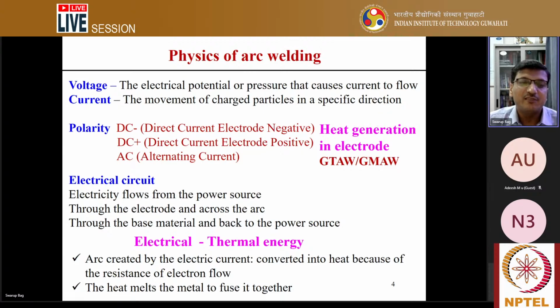So with this alternating way, both the cleaning action as well as the welding action are possible in the case of low melting point material having high affinity to form oxides. So aluminum is more suitable with AC current. We can use AC current specifically when you try to join aluminum. Anyway, fusion welding of aluminum itself is difficult, not easier as compared to steel. So other methods can also be used. That's why for aluminum welding nowadays, people try to use solid state welding processes. Mostly friction stir welding process can be utilized.